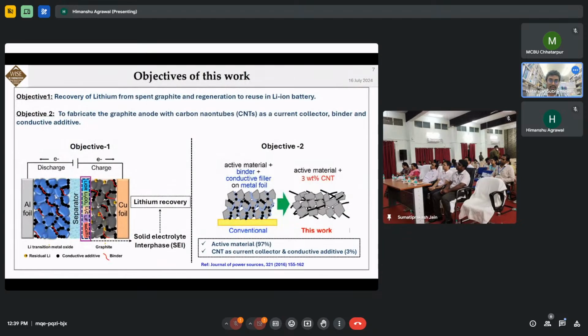The objectives of the work are, first, the recovery of lithium from spent graphite and regeneration to reuse in lithium-ion batteries. The second objective is to fabricate the graphite anode with carbon nanotubes as a current collector, binder, and conductive additive. You can see from the figure for objective 1, during the charging process, lithium ions will travel from the cathode to the anode, and during discharging, they will travel from the anode to the cathode. What happens during charging and discharging is that the solid electrolyte interface will form. The solid electrolyte interface consists of a number of lithium salts. As you can see from this figure, it might be lithium alkoxides, lithium carbonate, lithium oxide, lithium fluoride, or other hydrocarbon-related lithium compounds.